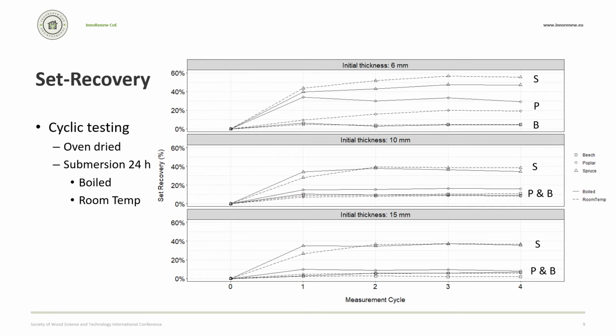To test for set recovery performance, we performed cyclic testing, which first oven dried the samples and then submerged them in water for 24 hours. This was repeated 4 times. 2 cyclic test series were performed for all specimens that used either boiling or room temperature water.